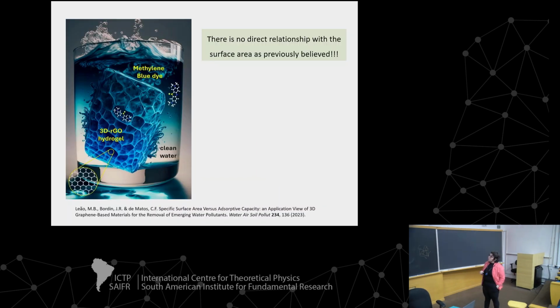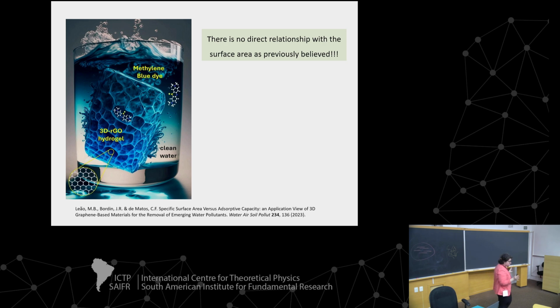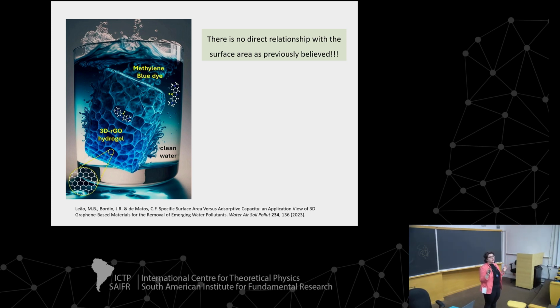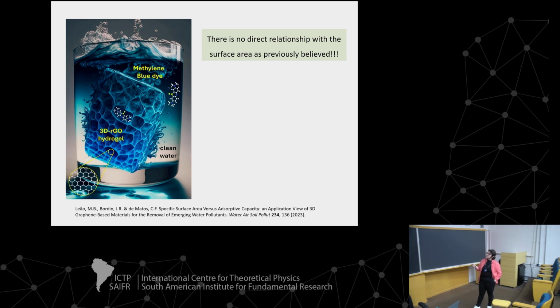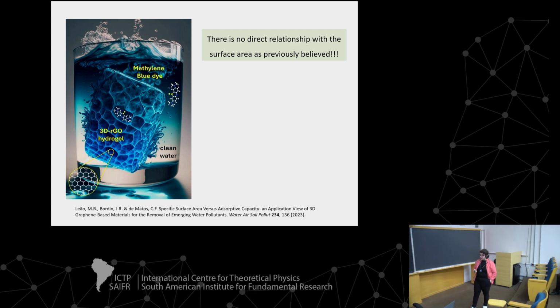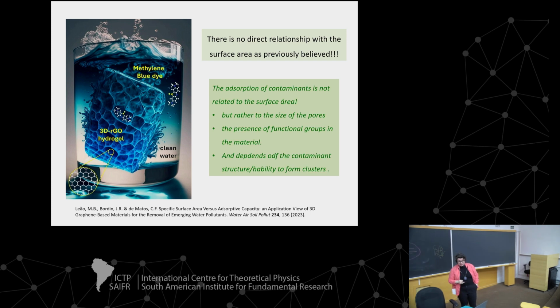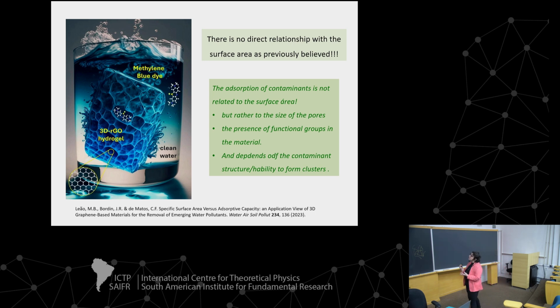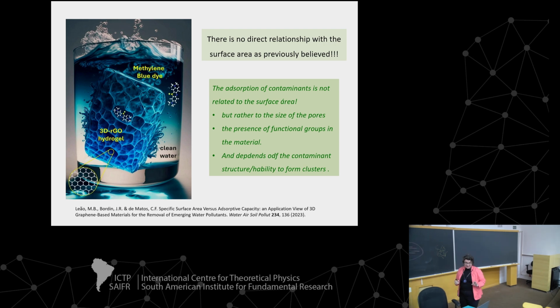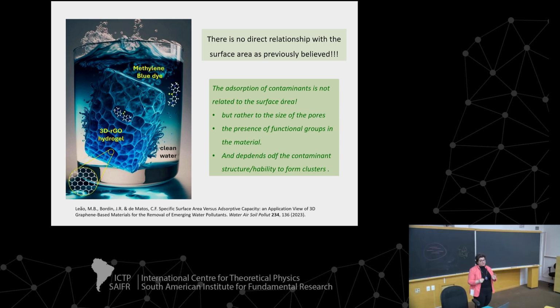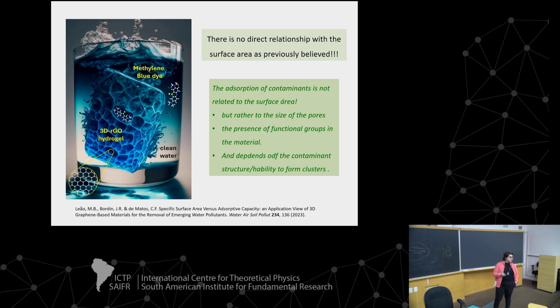So we break a traditional thinking that the higher absorption in graphene sponge materials is related to high surface area. Not necessarily. We did a very systematic review that we published, and with our studies, we showed there's no direct relationship with the surface area as previously believed. And the adsorption of contaminants is not related to the surface area, but rather to the size of the pores, the presence of functional groups in the material, and mainly depends on the contaminant structure and its ability to form clusters. This is a break in the previously believed knowledge about adsorption in materials.